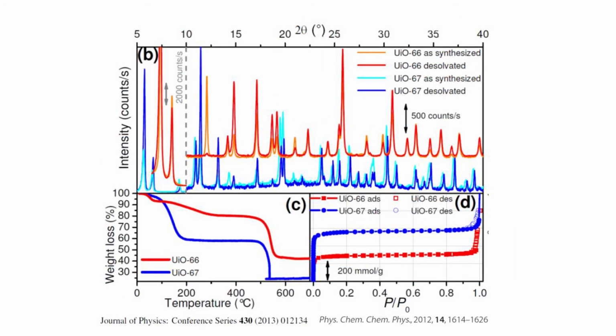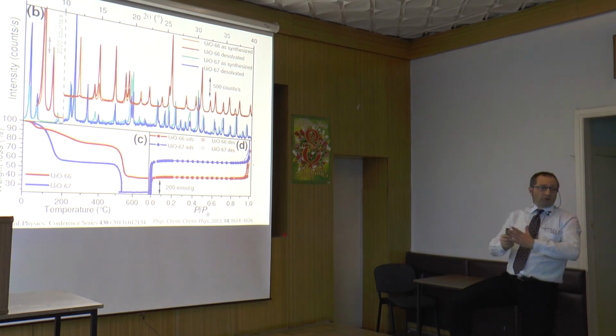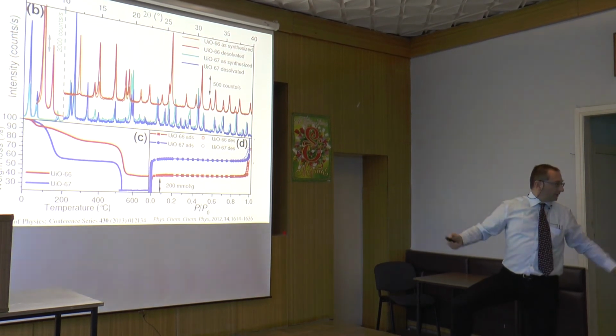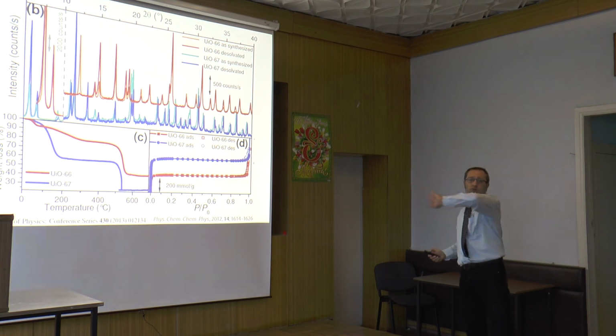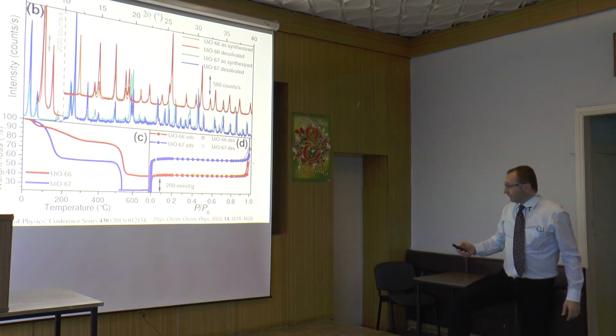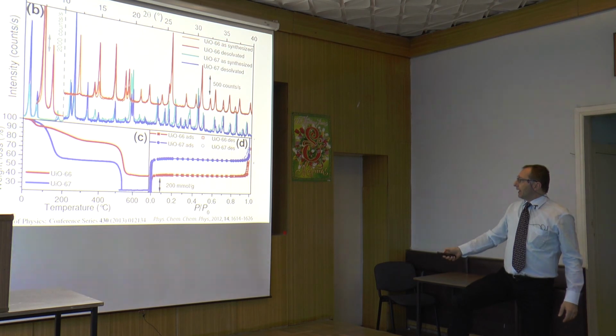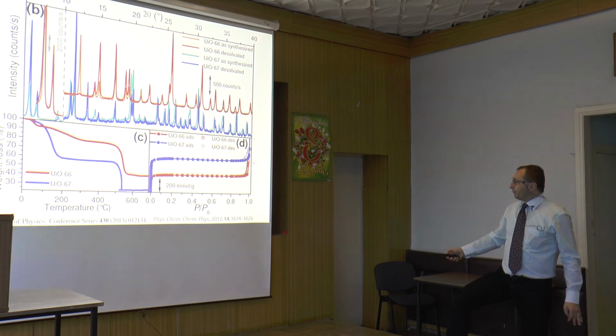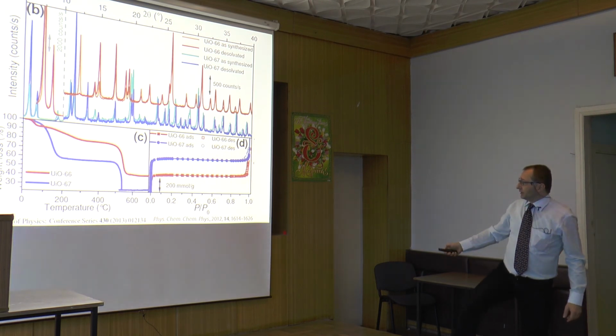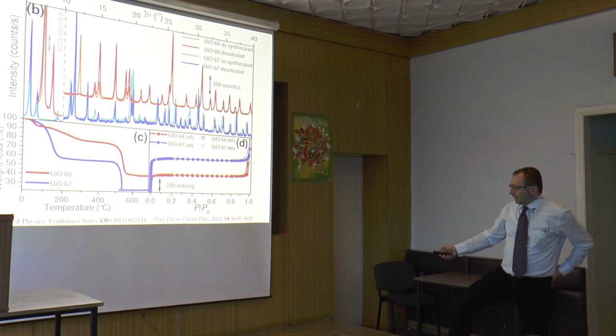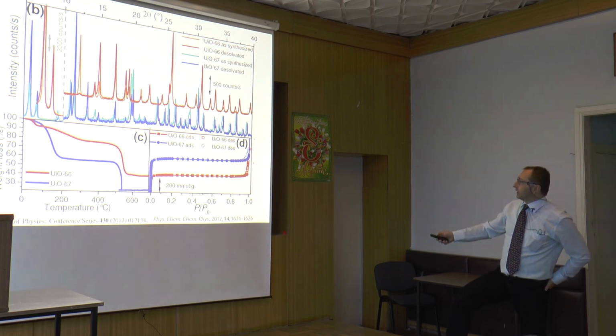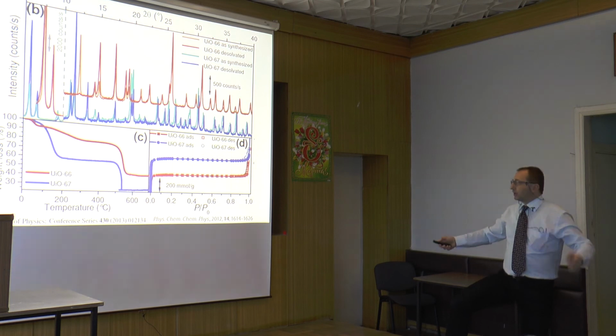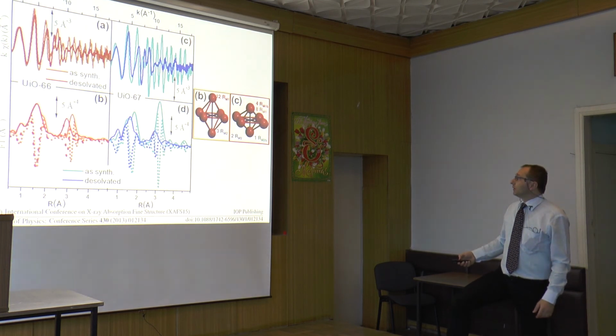We check the structure, so the structure is exactly the same, simply that you will see the peak shifted because the lattice parameter has been increased in this case, so all the peaks are squeezed to low theta values. We have the same thermal stability, but we will have a big difference in the porosity. So this is the BET experiment, the isotherm of nitrogen adsorption. We can see that in the UiO-67 with the longer linkers we have a much higher internal volume.